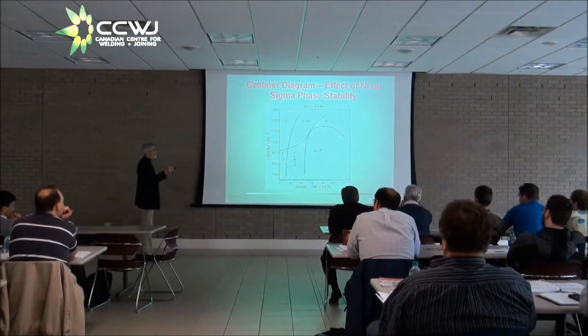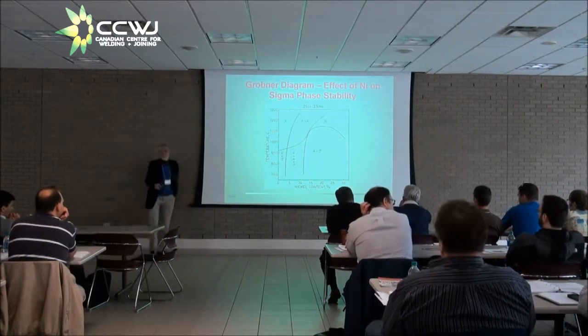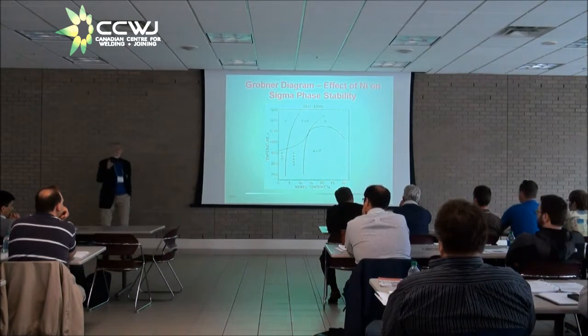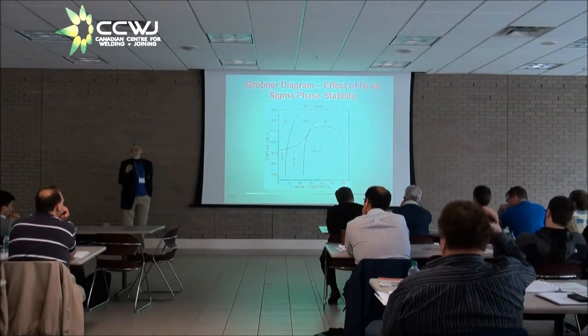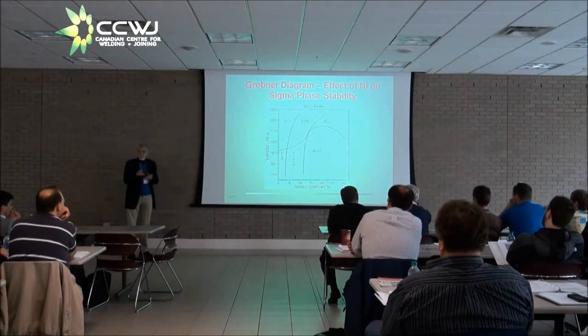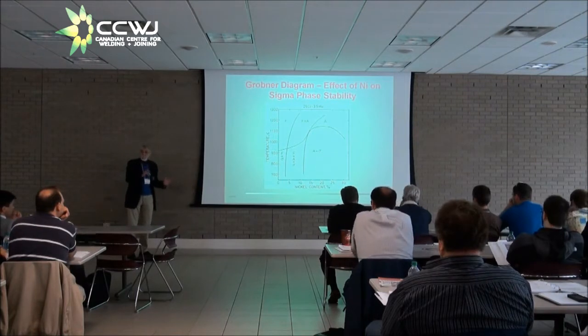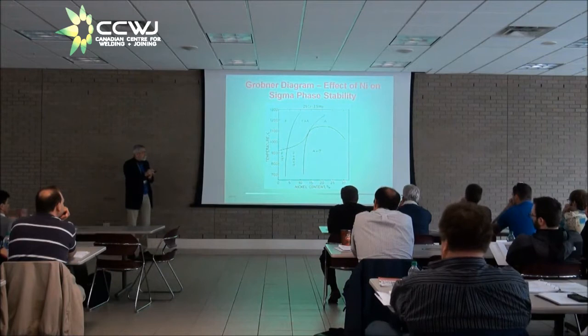So what you have here now are temperature fields for 100% ferrite, ferrite plus austenite, austenite, ferrite plus sigma, ferrite plus austenite plus sigma, and austenite plus sigma. The important feature of this diagram is the sigma solidus boundary. That's the boundary above which sigma vanishes. And here you can see that as the nickel content increases, the temperature of the sigma solidus rises. So when we went from a 5% nickel base material to a 9% nickel filler metal, we raised the sigma solidus temperature by about 100 degrees Celsius. Grobner's diagram was there, but nobody saw it.